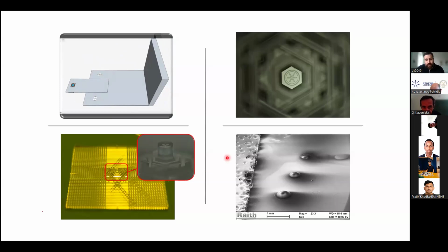On top of that, we are trying also to have full control of the conformation of the polymer on the apex of the pillar. This is very fresh. We are trying to etch structures on the surface of the pillars, like this one here, and we are running some tests. This way, the polymer will drop cast and it will stay within the limits of the structure, and it will create a very nice uniform dome, and we will have high selectivity, and there will be no danger of the polymer getting off the edges of the pillar. So we are running several tests to see what structure is the optimal one for this situation.